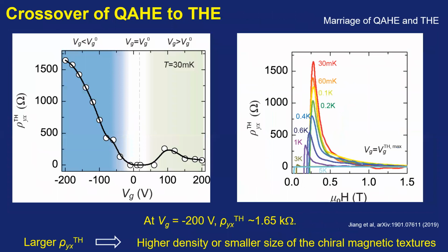So let's summarize the topological Hall effect as a function of the gate voltage. We can say that at this charge neutral point, the topological Hall resistance is 0. So this is just the quantum anomalous Hall regime. When you inject some hole carriers or electron carriers, there is a topological Hall effect, and the maximum of the topological Hall effect shows when the chemical potential is crossing the bulk valence band. And in the electron-doped regime, the topological Hall resistance is lower than this side. So there is an asymmetric behavior in this p-doped and n-doped regime.